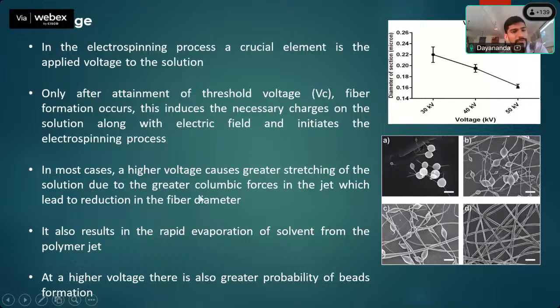This increases the evaporation rate of the solvent from the polymer jet. As you increase the voltage, the evaporation rate will also be more. During electrospinning, in the presence of electric field, the polymer solution comes out from the jet, and during its travel from the needle tip to the collector, the solvent evaporates, reaching the collector as just polymer with whatever additives we added during preparation. So the selection of solvent is very crucial, and the applied voltage is also very important.